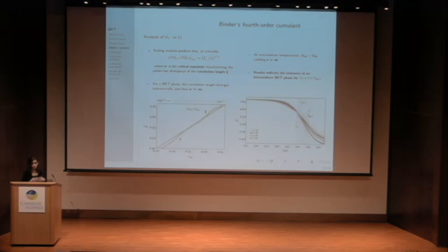So we have computed this for several pairs of sizes, and here we show, for instance, Binder for size 26 versus 24, and you see that at low temperature the data makes a bump, which is a characteristic feature of long-range order, followed by a straight line, and then deviates downwards at high temperatures, this last trend being characteristic of a disordered state. So in the middle regime, the slope is equal to unity, which enables us to then say that nu is infinite, which is concordant with what one would expect within a BKT phase.